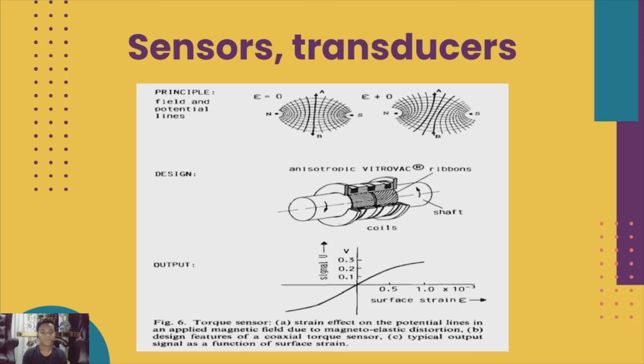Sensor transducer. The underlying torque transducer principle is illustrated in figure 6a. The potential lines of an applied magnetic field are displaced by a magnetoelastic interaction which can thus be monitored in a secondary inductive circuit. The actual concentric design which minimizes the effect of inadvertent geometric asymmetry on the magnetic signal is drawn schematically in figure 6b. A typical output signal as a function of strain is shown in figure 6c. Whereas the original torque transducer was thought to use the magnetic properties of the shaft itself, the utilization of an amorphous layer was recognized to give a much higher and reliably controlled output signal.